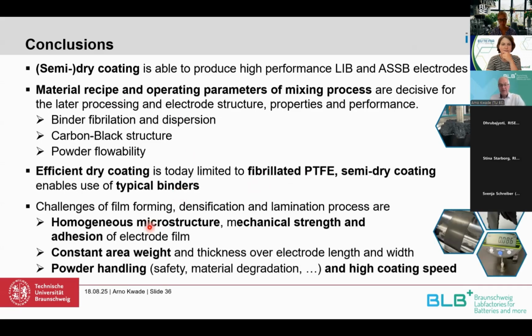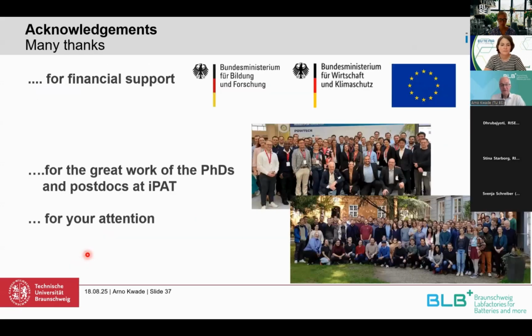And there are still some challenges, but I think there's big progress, and industry is really starting to use at least this dry coating method in a standard industrial production of battery electrodes. So we need a homogeneous microstructure with a good adhesion also to the electrode current collector. Then constant areal weight, powder handling, and so on. But I think these are challenges which can be solved really nicely.